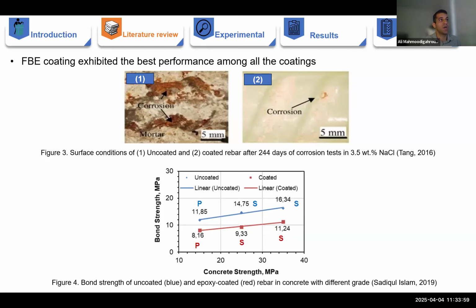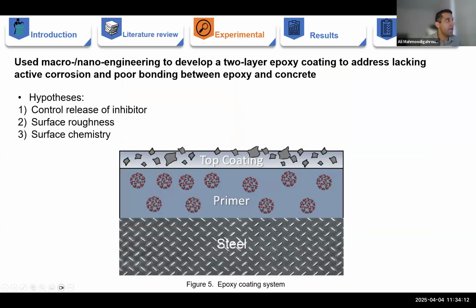Now coated rebar is hydrophobic. They don't like each other. They're not compatible. And these prevent both physical and chemical bonding between coated rebar and concrete. In my research, I used micro nano engineering to develop a 2-layer epoxy coating to address these issues.